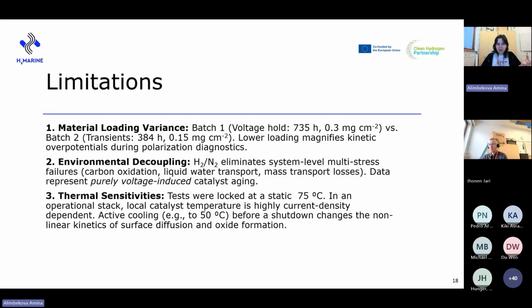In an operational stack, the temperature is current density dependent, and active cooling before shutdown — which could be an engineering strategy to reduce degradation — will also change the kinetics of oxide formation and the oxidation reduction cycles.